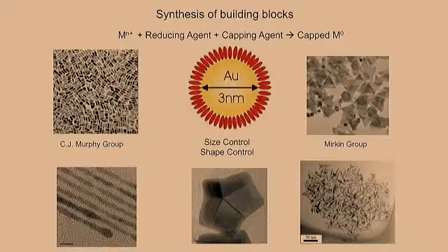You get monomers of gold, or basically gold in the 0 oxidation state, that have to come together to form the crystal. Classical nucleation theory, homogeneous nucleation theory, tells you that initially there will be a few attempts, the crystal forms what are called embryos that are not stable and dissolve, but once it crosses a critical size, you get what is called the stable nucleus. That stable nucleus is basically set for growth, essentially, right?